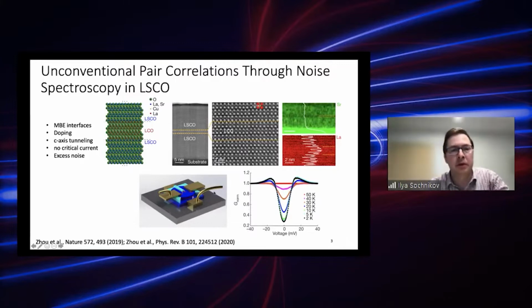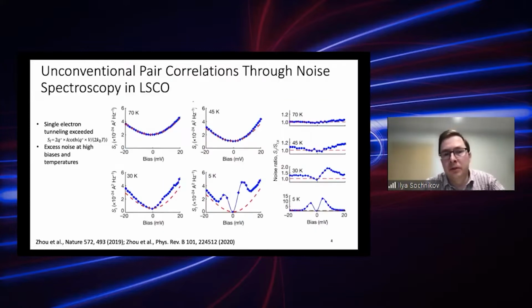So basically, these layers are quite insulating, which was to some extent a surprise, but it actually played in a good way for us, because the high resistance of these layers somewhat enables us to see noise in the tunneling current better. So we measure the current and take the autocorrelation of the current, and that's your electronic noise. Here I'm showing data from underdoped samples. Starting from 70 Kelvin, the dashed red line is essentially a model for resistor noise, and it follows the data pretty well.